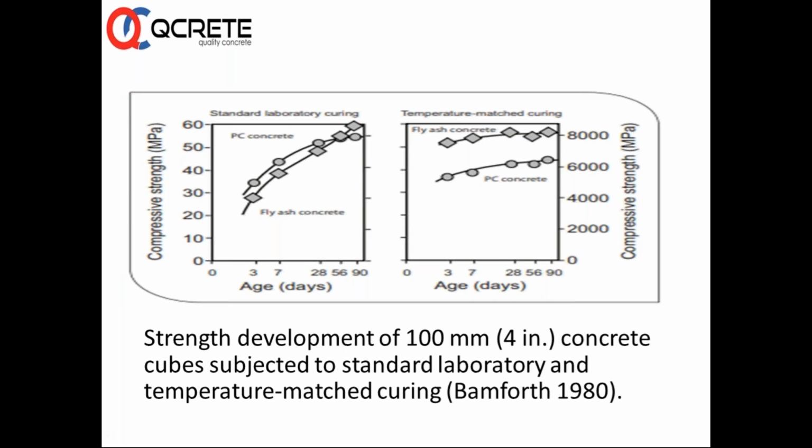As I said earlier, even if, for example, a concrete mixture, say M25, just touches the characteristic strength of 25 newtons per mm square in 28 days, even though some sets of these cubes may slightly be questioned as per IS criteria for passing, it is certain that if it touches even the characteristic strength in 28 days, you can expect an increase of 8 to 15 MPa between 28 days and 90 days, depending upon the mineralogical characteristics and the interaction between OPC and fly ash.